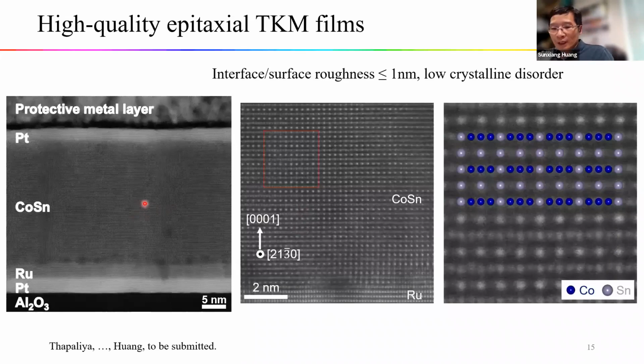To further confirm the crystalline quality, we did the TEM measurement. So here it shows these films have quite well layered structures. The interface roughness and the surface roughness are roughly less than 1 nanometer. The high magnification scanning TEM image shows the desired atomic arrangement with low crystalline disorder.